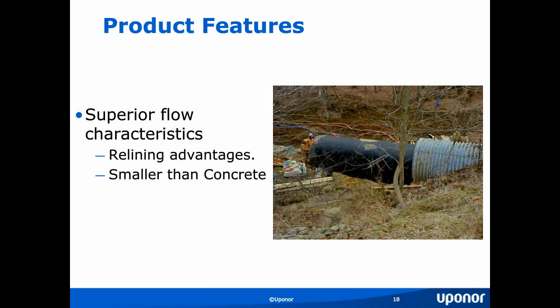Weholite pipe also has superior flow characteristics. As you can see in that particular photo, in this particular project, we are relining a corrugated steel pipe after it has shown considerable wear and corrosion. And because of the Manning coefficient of 0.01, we are able to actually reline corrugated steel pipe and actually increase or at least maintain the flow going through the smaller diameter Weholite.